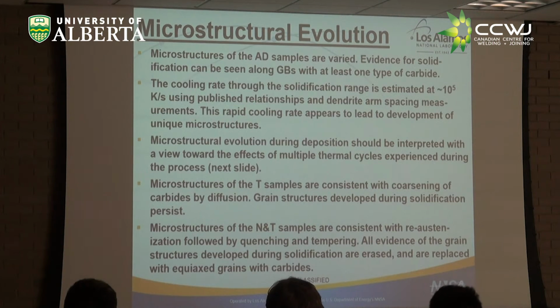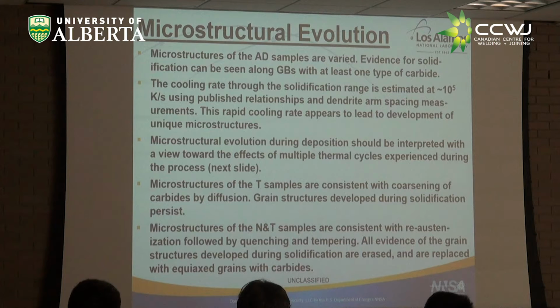So we see the microstructures of the as-deposited sample, I think you'll agree, were varied and confusing. We see the evidence for solidification, and there's at least one type of carbide present in the microstructure. If you go to the literature and look for dendrite arm spacing versus cooling rate relationships, you won't find one for this material. You can find them for stainless steel, which this is not. This is a 9 chrome. Stainless steel has a minimum of 12% chrome. But if you use some of those numbers, you can estimate maybe the solidification cooling rate.